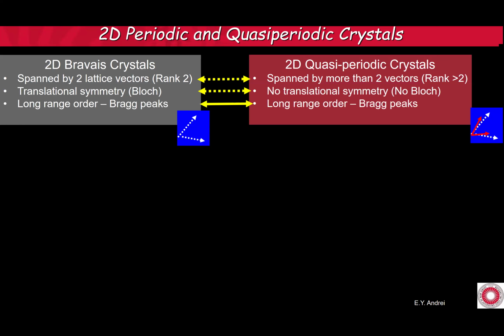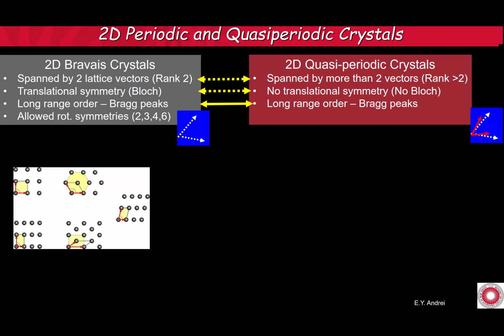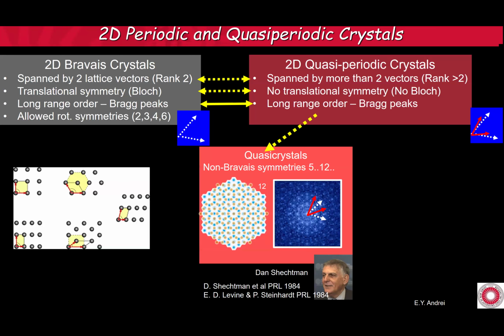And then you can look at long range order. Both have long range order, and that is manifested by the fact that you have sharp Bragg peaks. And then you can look at the allowed rotational symmetry. On the left, we have only 2, 3, 4, 6. On the right, it depends. So we have the well-known quasicrystals, which have all these properties, but they have rotational symmetries other than the Bravais symmetry. Experimentally, they're very rare. They're in aluminum manganese, and they have a 5-fold symmetry. Do you have other symmetries? Decagonal, 10. Okay, we have that too.